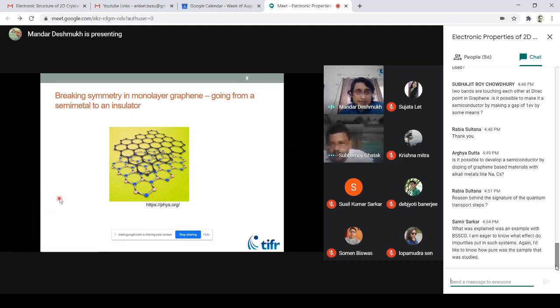So let me explain this idea. The fact that graphene is metallic or semi-metal like, that it doesn't have a band gap, arises from a basic symmetry: there is an inversion symmetry across the crystal. If about the center of the top black hexagon, at the center point, I make all the lattice points x go to minus x, which means basically inversion, you get back the same lattice again. This simple symmetry, that the lattice has inversion symmetry, guarantees that you will have no band gap.